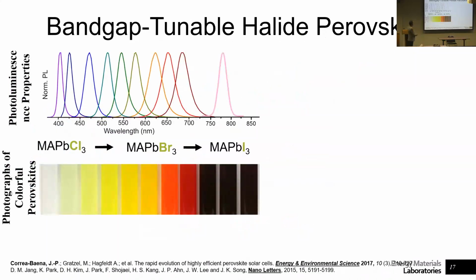Okay, so what happens when we go from chlorine to iodine and we explore combinatorial structures of materials? We go from a material that absorbs in the UV, so we can make UV absorbing solar cells if we want, or we can make a UV detector, for example, to bromine based, which are going to be more yellow, red. So if we were thinking about building integrated photovoltaics, for example, and we're interested in color, we can start looking at bromine-based perovskites. And in the near infrared, we have the iodine-based perovskites.